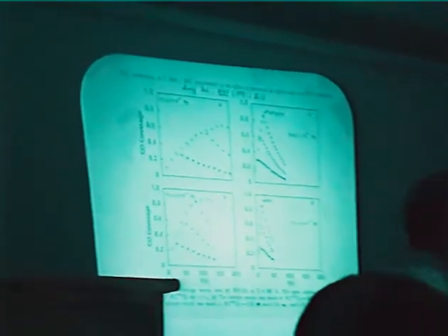And please notice that, for instance, at the coverage of 0.3, this is the rate of desorption, and this is also the rate of desorption at higher pressure, at the same coverage, 0.3. So you can notice that the rate of desorption is dependent upon the pressure in the ambient. And of course, the computer gives much better results than experiment.